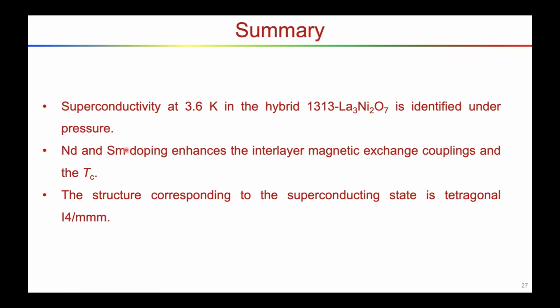Here's a simple summary of my talk. We found superconductivity for this 1313 phase at 3.6 Kelvin, and neodymium and samarium doping enhances the interlayer magnetic exchange coupling and also enhances the TC. The structure corresponding to the superconducting state of the bilayer 327 compound is the tetragonal phase.